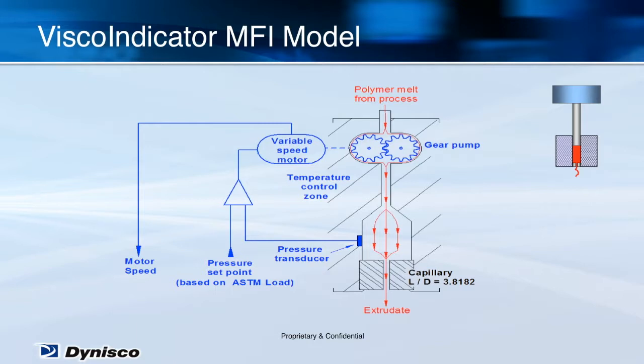The temperature of the steel around the capillary and the pump is controlled, and a single pressure transducer is located above the capillary to measure driving pressure. The test polymer extrudes to atmosphere. By that I mean it falls to the floor, just like it would in the melt flow indexer. All material that enters the rheometer flows out as scrap, typically at the rate of 1/2 kilogram per hour. This rheometer duplicates the internal geometry of the melt flow indexer, so the capillary entrance effects are similar.